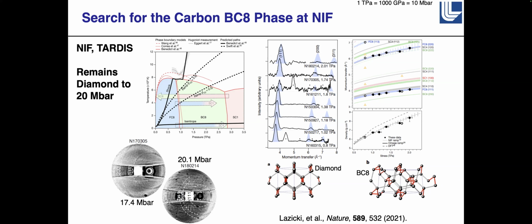And it turns out that the ablation plasma is emitting so many X-rays that our background is extremely high. We've tried to filter off the smooth background, but our signal to background for this 111 peak at the highest pressures, which is shown here, is about 1 to 200. So signal to noise is not that low because we can subtract off a smooth background, but it just gets so hard to pull anything out because you've got so much background from the X-ray diffraction, which makes it really exciting because we won't have the same problem with synchrotron and XFEL experiments because we can do much better filtering of the X-rays.